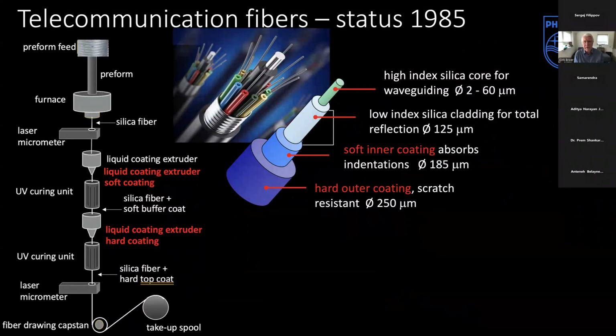The quartz fibers that are being used for that are intrinsically very strong, but when you draw them from a preform, as shown on the left slide, you start with the preform, and then you melt the material. The preform already has a refractive index gradient needed for the total internal reflection of the light, and then when molten, you take it up on a spool.